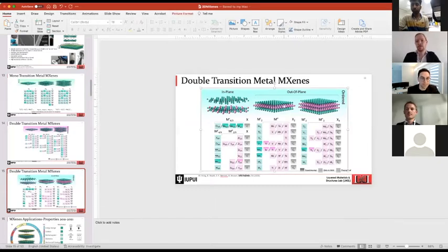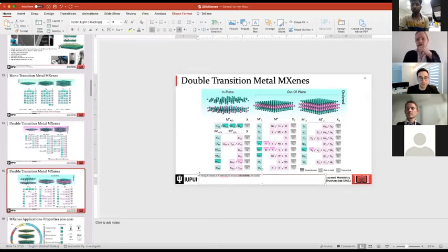The double transition metals have been predicted to be semiconductors when we have a uniform surface termination. Everything that we have measured so far had a mixed surface termination, so that's why we found it to be more resistant, and we did not observe any semiconductor behavior. It was more metallic-like. I do not have the reference here, but you can find it in this review paper, a study that we published when I was at Drexel in 2016, where we showed how we can tune the electronic properties of MXene by just playing with the core transition metals.